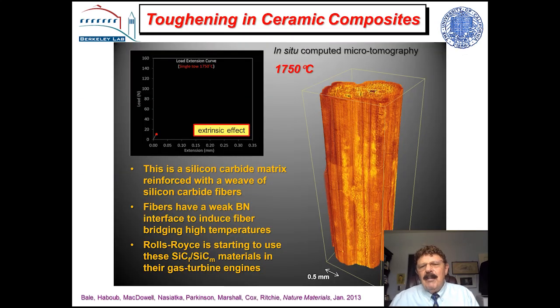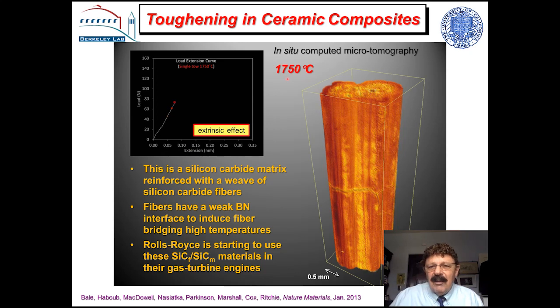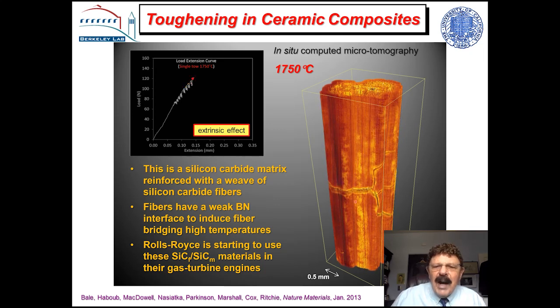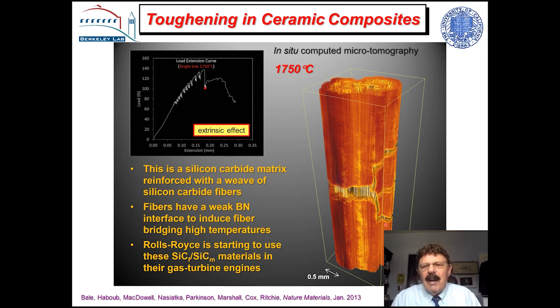Now, the other extreme is a ceramic, which is purely extrinsic. This is a silicon carbide reinforced with silicon carbide ceramic. These are materials that are now being put into jet engines by Rolls-Royce and Pratt & Whitney and GE. This is a particularly high temperature version. This is a tensile test that we're doing in the synchrotron at a ridiculously high temperature of 1750 degrees C, and we can do the tensile test and see what's happening at the same time. You see a crack developing here, and you can see the bridging by the silicon carbide fibers.